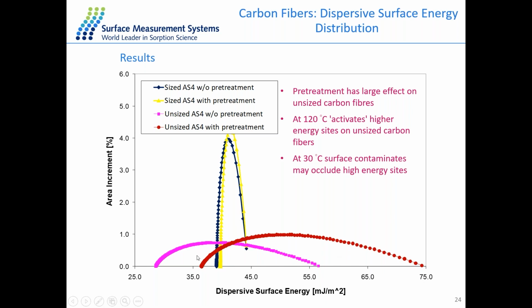In this case, we can see a very distinct difference between treating our sample at a higher temperature versus doing our experiment at a lower temperature of 30 degrees. What this tells us is that at 120 degrees, we're activating some higher energy sites on our carbon fibers. Because of this, our probes can interact with these higher energy sites and give us information that this is much more heterogeneous. However, at 30 degrees, we don't have enough energy to eliminate any of the adsorbates that may be blocking these sites. Therefore, we have a more homogeneous material. So conditioning our material has a very strong impact on what active sites are available on our surface.